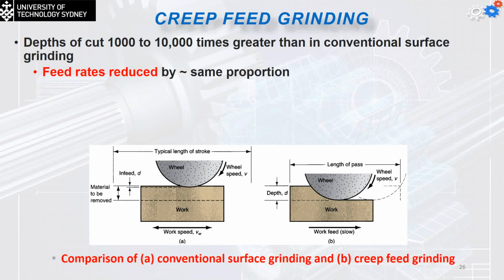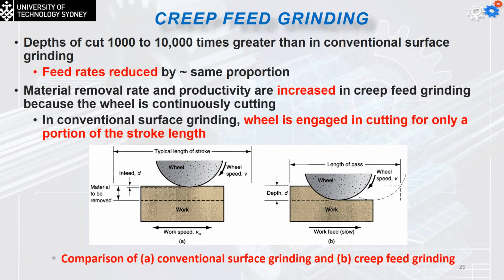The feed rates are going to be reduced by almost the same proportion. So because we're removing the material at a higher rate, we cannot do it with the same velocity, so we reduce it by the same value. If I'm going to increase the depth by 1,000 times, I have to reduce the velocity by 1,000 times. The material removal rate and the productivity are going to be increased in creep feed grinding because the wheel is going to be continually cutting. In conventional surface grinding, the wheel is going to be engaged in the cutting for only a portion of the stroke length.